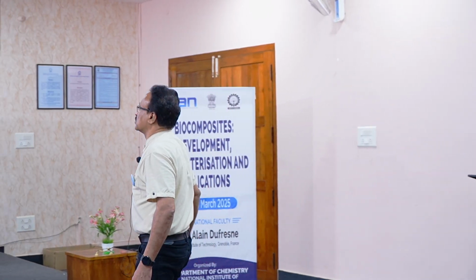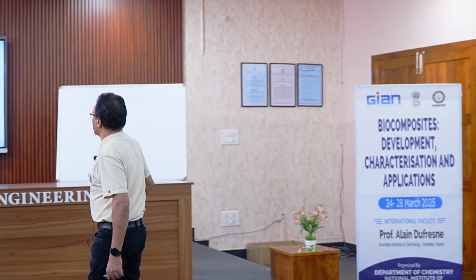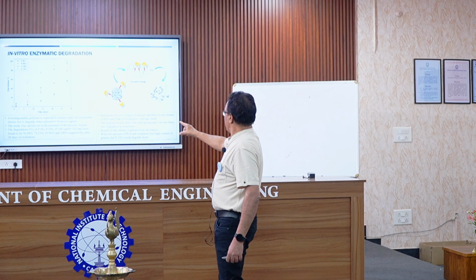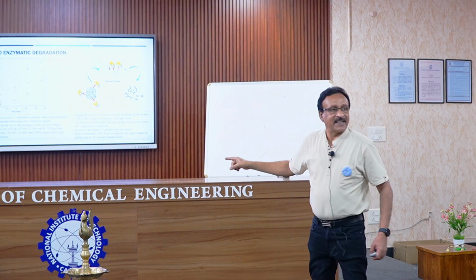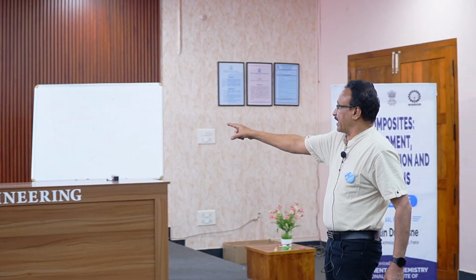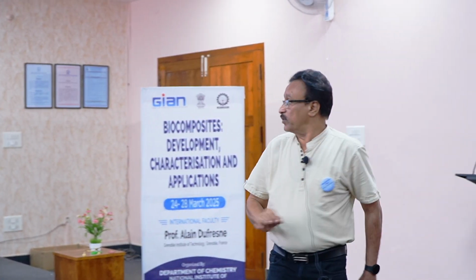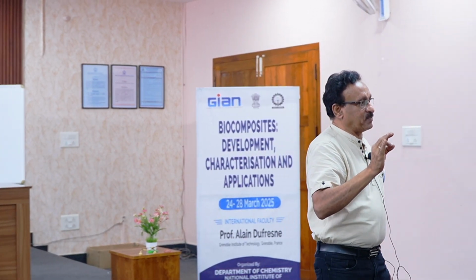At that time the material started degrading. You can see that over a period of time, degradation profiles are given there. The material significantly undergoes degradation. Degradation of P10, you can see that P10 happened 95% over a period of time. After 28 days, within 1 month, this biocomposite, this biosystem, 98% of its weight is degraded.